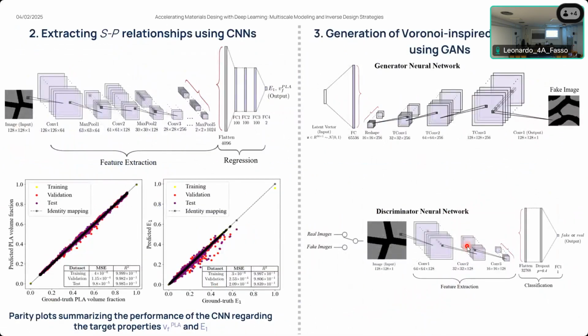As already introduced, the second step is, again, training a predictor module, which is based on a convolutional neural network. Again, a very good agreement is obtained for the 2 target properties. The target properties in this case are the Young modulus on the first axis of the global reference frame. And in order to introduce a kind of constraint in the optimization process, the second target property is the volume fraction of the stiff phase, in order to be able to target specific material properties by also constraining the volume fraction of one of the 2 phases.